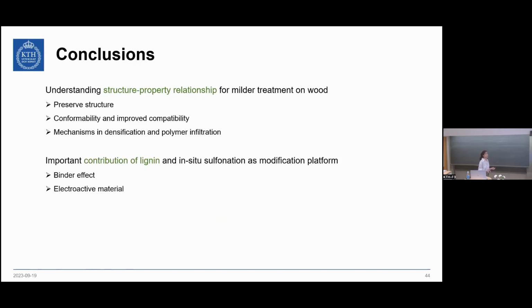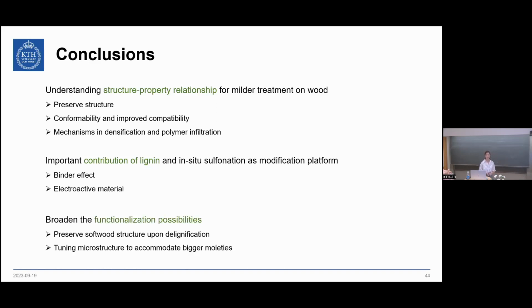Secondly, we could see how important it was to preserve the components, especially lignin, which in the first section was very important to act as a binder for the thin film, while in the second section, it could be used as electroactive material for energy applications. Finally, we could also see how different wood modifications can broaden the use of wood in functional materials. In the very first study, because it was possible to completely delignify wood without it falling apart. And in the very last study, we could see how it's possible to tune the microstructure of the wood cell wall so that it can actually host bigger moieties.